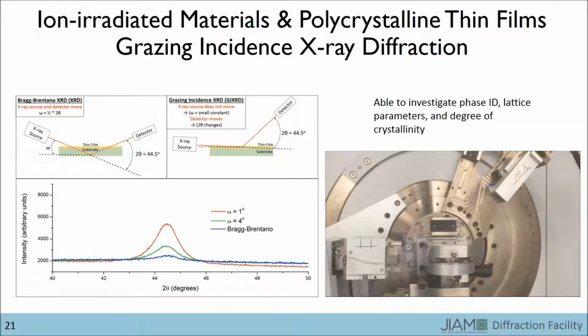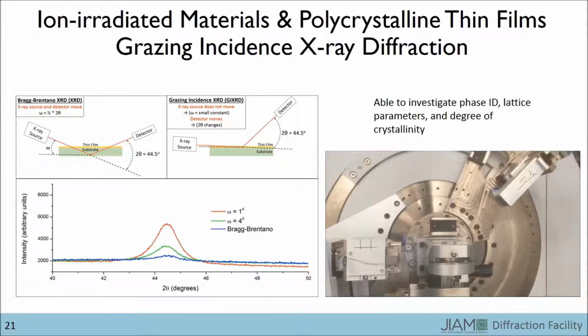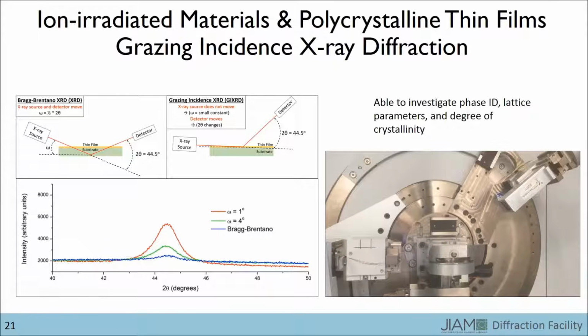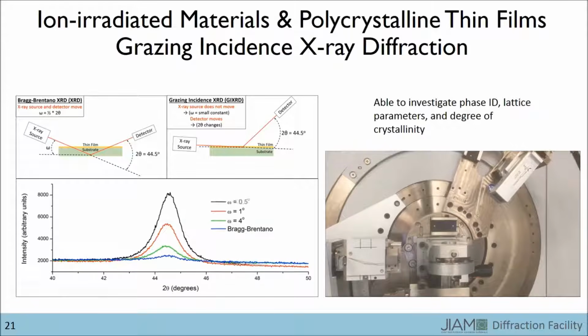Finally, the grazing angle is reduced to half a degree, and as you'll see in a moment, the peak intensity increases further. Now, in case I'm leading you to believe that the peak will continue to get larger as you decrease the angle, there is some angle at which the X-rays no longer penetrate into the material and you stop seeing peaks altogether.